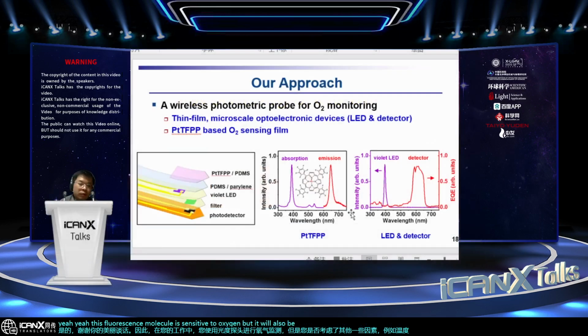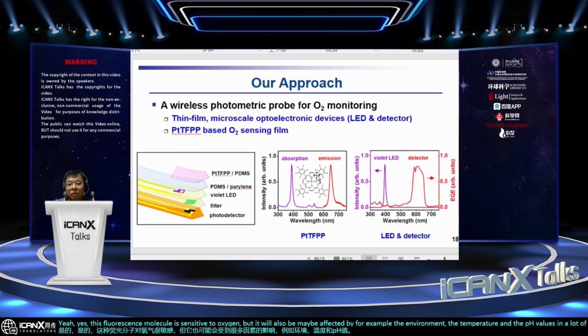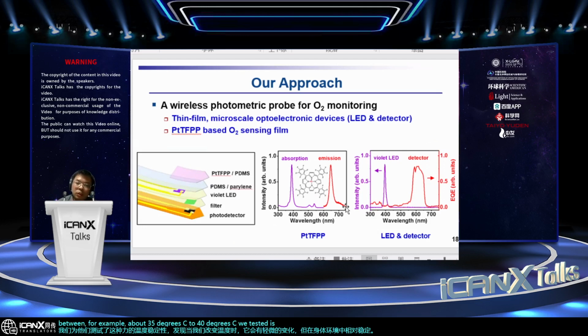Yes, this fluorescence molecule is sensitive to oxygen, but it may also be affected by, for example, the environment temperature, the pH value, and a lot of factors. We tested the temperature stability of this phosphor, and we found it has a slight change when we change the temperature, but it's relatively stable in the body environment, for example between about 35 degrees C and 40 degrees C. We tested it, and it's quite stable in this small temperature range. In our body, we know that temperature will not change too much, usually just about 1 to 2 degrees C. Okay, thank you.